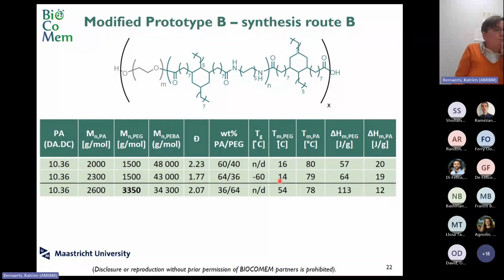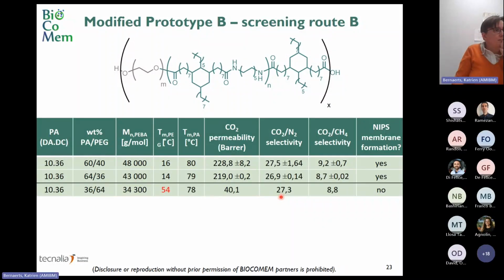The melting point of the PEG is below the processing temperature if we use a low molecular weight PEG of 1,500 grams per mole. But when we use a high molecular weight PEG that is also more crystalline, of 3,350 grams per mole, the melting point of the PEG is 54 degrees, which is not preferential for the processing. And this is what you also see in the screening results.